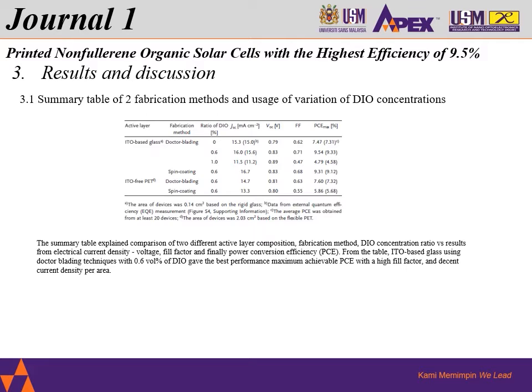When we're just taking a first glance over here, you can see that there's 9.4% of maximum PCE reported out, and this is using ITO-based glass, doctor blading fabrication method, and 0.6% of DIO. In regards to that, we also have a very high fill factor, which is around 71%.